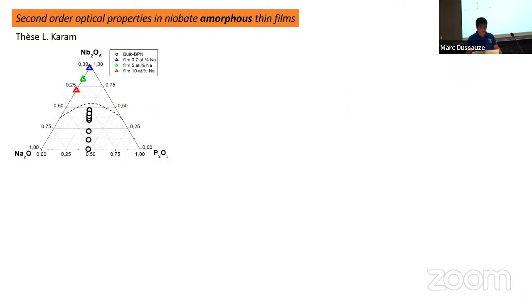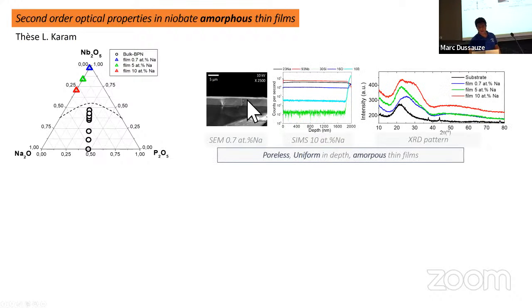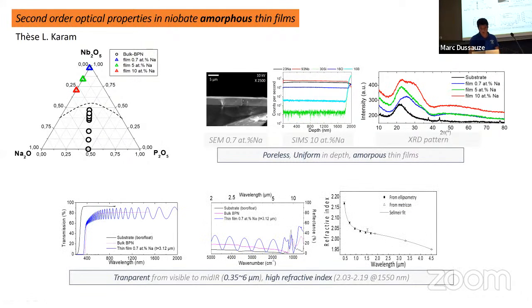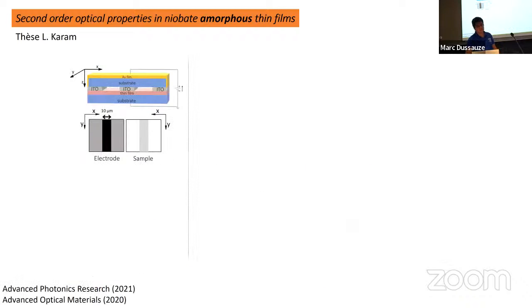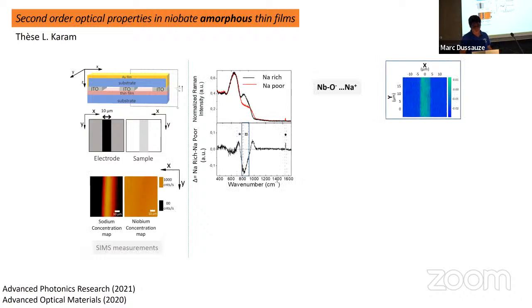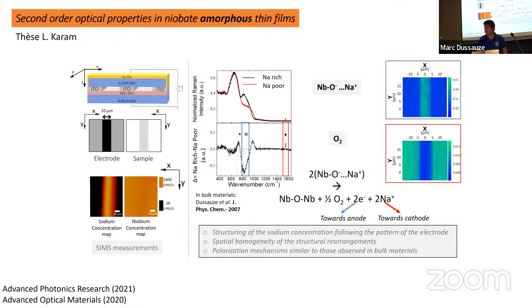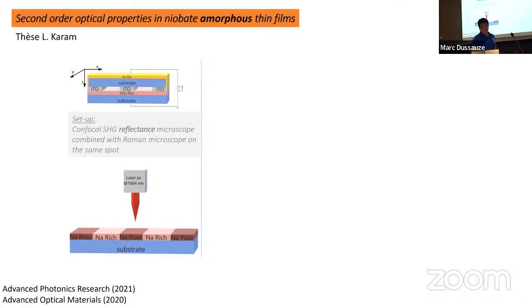So this is what we have done for these niobate films. We obtained very nice amorphous materials with good optical properties. But the most interesting point is that it reacts very well to the poling. And so we can use all the methods that I have shown you before. This example explains how we can modify the thin film structure locally using this imprinting method. And I want to focus more on the nonlinear response.